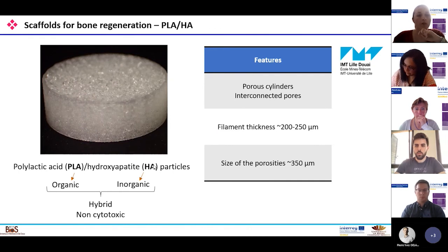So we decided to use this technique to print 3D scaffolds for bone regeneration, and we chose PLA and hydroxyapatite particles to mimic the organic and inorganic parts of the bone. And also we know that PLA and hydroxyapatite are non-cytotoxic materials which are already used in tissue engineering. And we then obtained these porous cylinders with interconnected pores. And the parameters were adjusted by IMT to obtain the required features for bone regeneration.